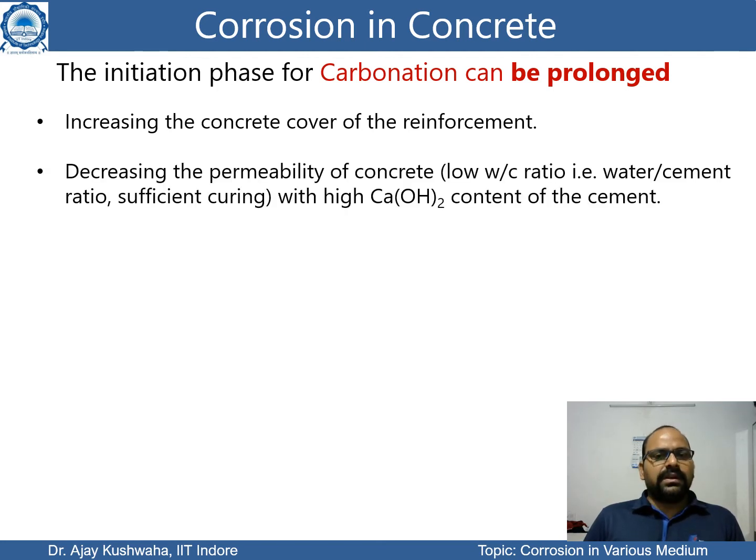The second point is to decrease the permeability of concrete, meaning a low water to cement ratio, sufficient curing, with high Ca(OH)2 content of the cement. So the idea is that if we use a high amount of water, then when it dries, it generally creates pores in the concrete structure.